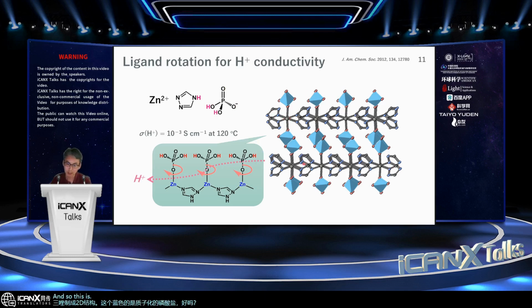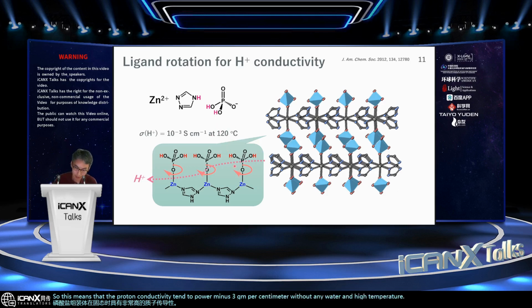This is the crystal structure, but if we heat to 120 degrees C, for example, the pinned phosphate starts to rotate very rapidly. Because of the extended hydrogen bonding, the proton can migrate through the phosphate assembly, giving a very high proton conductivity in the solid state. This means a proton conductivity of 10 to the power of minus 3 Siemens per centimeter without any water at high temperature, okay? So this is evidence that rapid rotation in the crystalline state, using metals and molecules, is a good approach to very high proton conductivity.